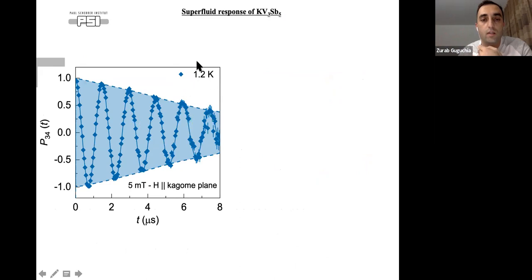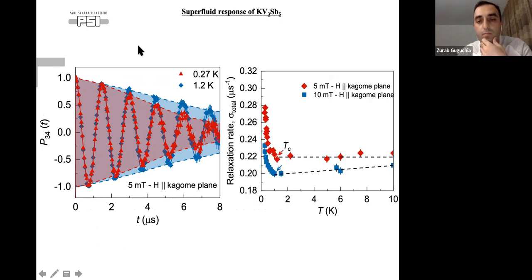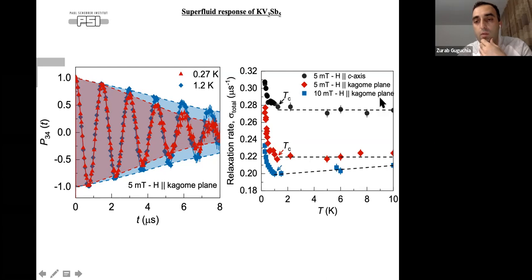So what we see is this is the normal state above TC. You have strong damping because of nuclear moments, but as soon as you enter the superconducting state, you have an enhanced relaxation rate because of the formation of the vortex state. And you see the relaxation rate increases just below TC when you apply field along the plane, or if you do it along the c-axis, we have some anisotropy at high temperatures, but you still see the increase of relaxation.